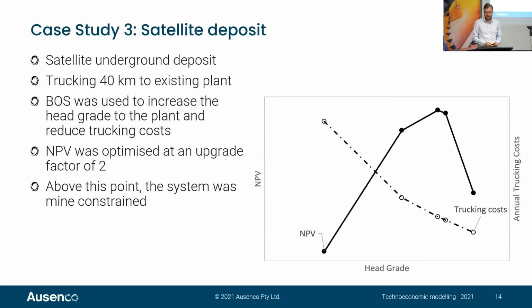And in this process, we had a look at the NPV as you change the head grade to the plant, and the trucking costs associated with that. And we found that there was an optimal upgrade factor of 2, where the NPV was optimized, and above that point, the system was mine constrained. So yeah, really interesting little case studies there that show that the application of this is really case specific, and that there's real value to be found by linking the technical modeling with the economics to be able to optimize for the goal.